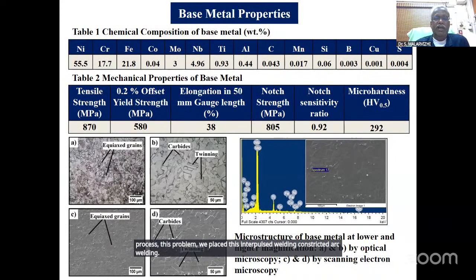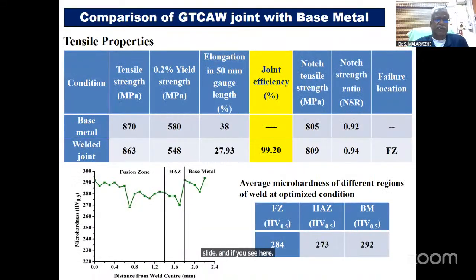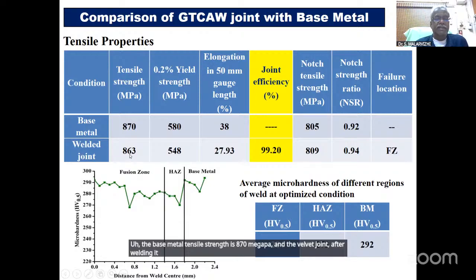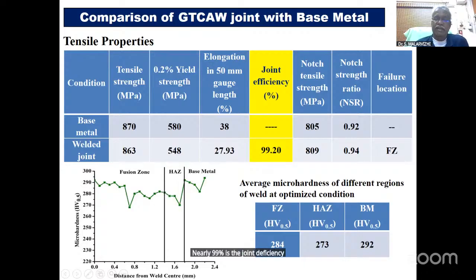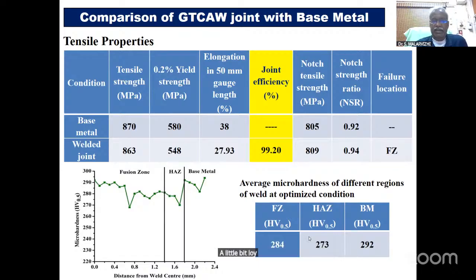We took the Inconel 718 alloy. The base metal details are given in this slide. If you see here, after welding, the joints were compared with the base metal. The base metal tensile strength is 870 megapascal, and the welded joint yielded 863 megapascal. That is nearly 99% joint efficiency. But failure occurs again in the fusion zone because the fusion zone hardness is a little bit lower. The fusion zone is 284 and the base metal is 292, so at the interface between the fusion zone and the heat affected zone, the failure has occurred.